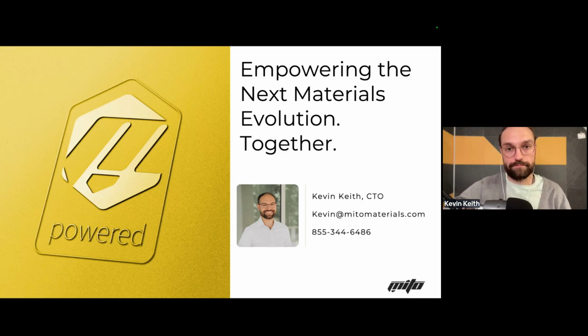Next question. You talked about improvements in electrical conductivity. Do you see the same trends in thermal conductivity? It totally depends on morphology and physical structure. If I have a larger but flatter particle, yes, but not 3x. Typically, with that 3x electrical conductivity, we have somewhat of a thermal conductivity increase, something along the lines of 20 to 30%, but definitely not 3x.